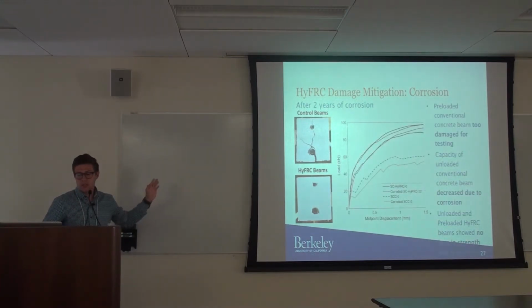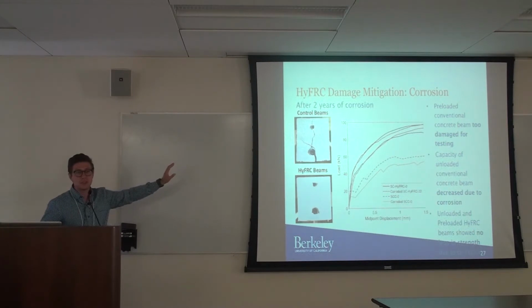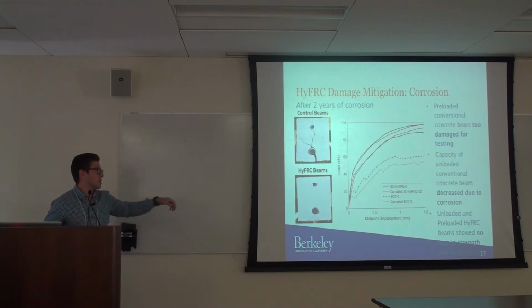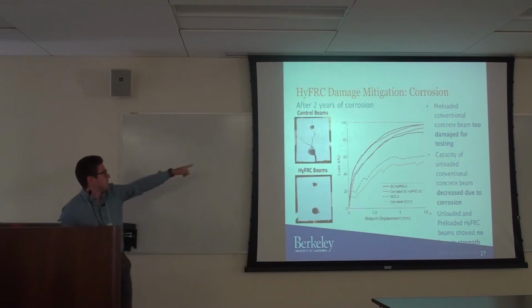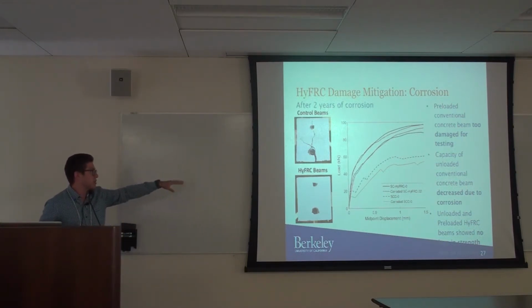And then here are some tests. The black curve is the original HyFRC beam with no corrosion. Red is with corrosion, at least the same length of time given to it. And so you see very little decrease in performance of those. Whereas with the conventional concrete, going from the black dotted down to the yellow, you see quite a loss in capacity. And this beam here that you see with that large crack, we weren't even able to do a proper test on that because it was so cracked, it had no capacity left.